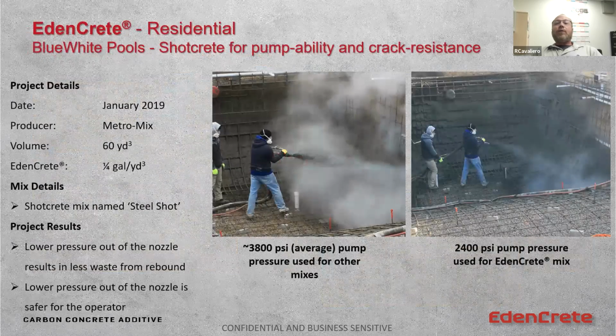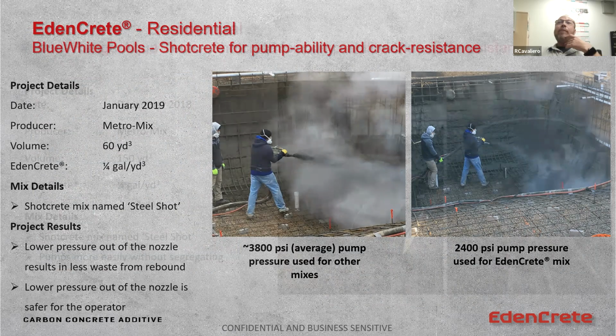So shotcrete. We started putting EdenCrete into shotcrete. We realized that suddenly it did not produce as much dust. It stuck to the wall better. We could see this visually when we went out onto a job. A hydraulic pump would be running at 3,800 PSI pressure. We put EdenCrete trucks up to it. It drops to 2,400 PSI on its own because it's easier to pump, right?